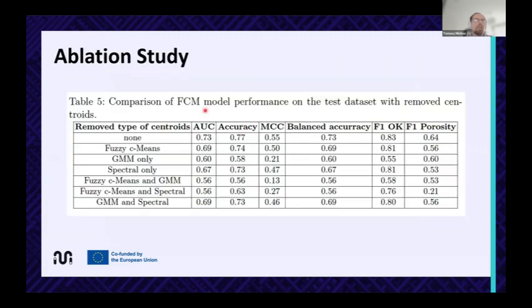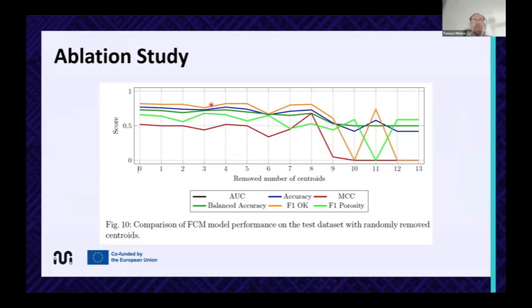We also made some kind of ablation study where we measured different parts of our architecture, how it performs. And for example, when we remove different types of centroids, we obtain different results of metrics. So we can see that when we reduce the number of the centroids, the average accuracy and balanced accuracy, AUC, F1 scores for both classes and MCC is decreasing very highly. So when using 13 centroids, up to 8, still the results were quite good, but when we removed more, the results were much worse.